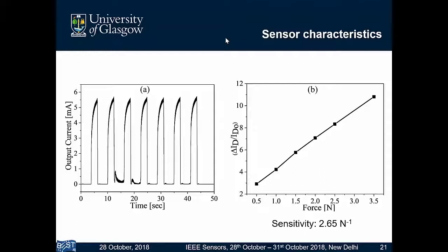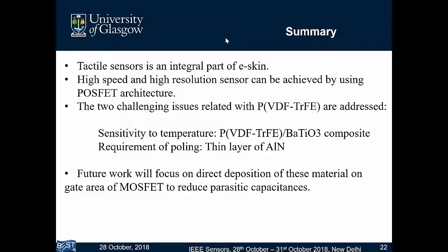Since it is an extended gate, we use a probe station plus a setup mechanism. The sensitivity we got is 2.65 per Newton. Sensitivity here we define as the normalized change in current per unit force. So we got a sensitivity of 2.64.